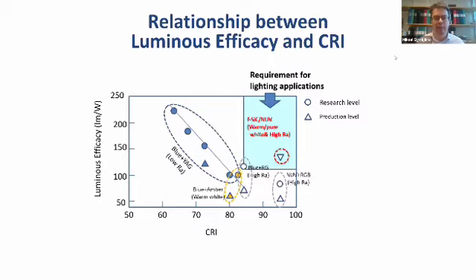So it can find its position once we have cleared out the physics to grow the material, understand the luminescence, and then fabricate this. The stage we are at now is that we started this research some years ago, but it was difficult to find funding, so it's slow progress. Basically, with these donors and acceptors, we need to find the correct concentration and also play with the relation. And we need to do this doping in the growth without damaging the crystal quality, because that kills the luminescence. So this is the stage which we have been exploring.